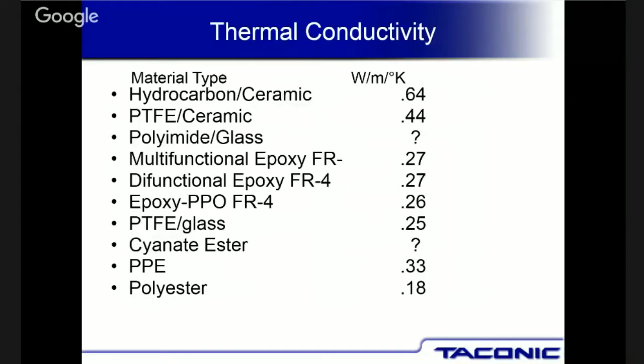And then I'm going to flip to the next page and I'll show you our numbers on all of our printed circuit board materials. So think about 390 watts per meter, and even the Teflon materials, PTFE glass, it's 0.25. So when you really look at it, we're insulating. We're really not doing much thermal conductivity in the printed circuit board materials. But some people find that if you can take a thermal conductivity of this material at 0.27 and raise it up to 1, our board's going to run cooler.